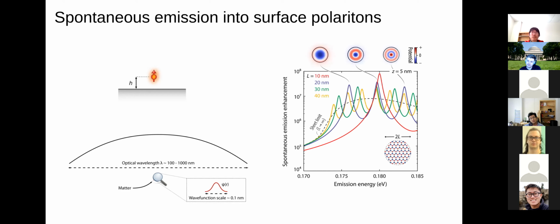So here's an example of the Purcell factor, which tells you the rate of enhancement compared to a free space transition of a two-level dipole emitter, which is placed over a nanodisk of monolayer hexagonal boron nitride, which supports surface phonon polaritons. And due to the nature of the confinement, if I recall correctly, I think the spontaneous emission rate enhancement actually scales as something like the confinement factor cubed in this case for a dipole transition. So something like a confinement of 100, if you cube that, you start getting these quite substantially large values of spontaneous emission rate enhancement. So it's not like it goes up by a factor of 5. It's like it's 8 orders of magnitude faster than it was before, which is really quite striking.